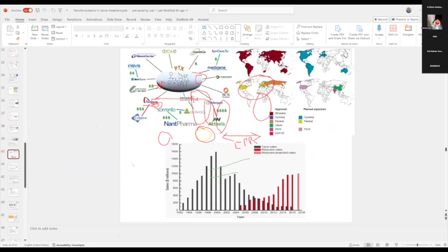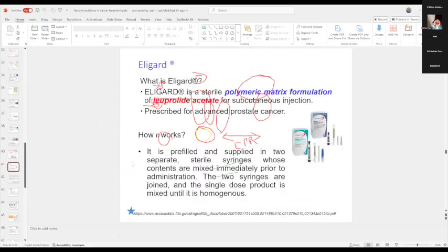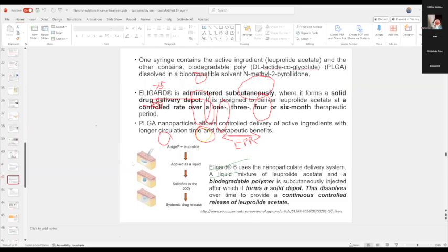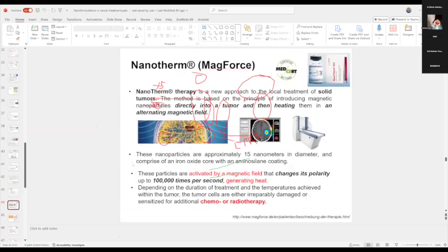Okay, so now with the polymeric matrix that is embedded with the leuprolide acetate, it can increase the delivery of the drug for over a couple of months. For example, based on your PLGA ratio to the drug, you can improve the delivery at the tumor site over a period of, for example, 1 month, 3 months, 4 months, and 6 months, depending on the depot that you are making, the composition of this PLGA matrix for this particular construct. There are many more examples like that.